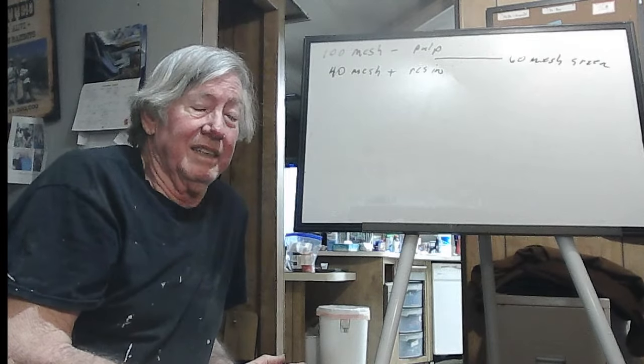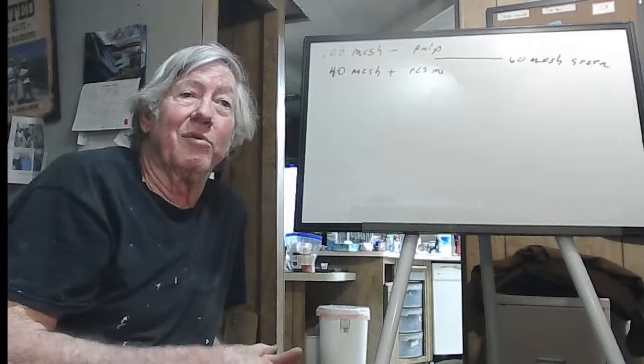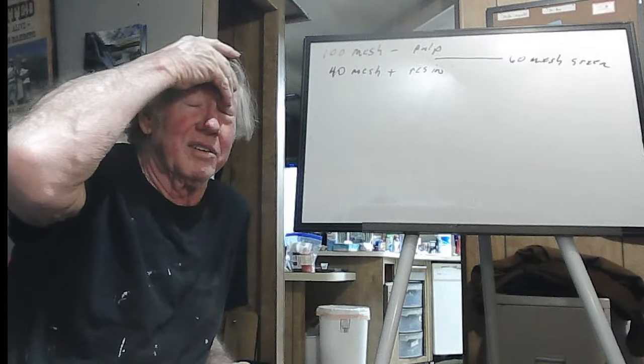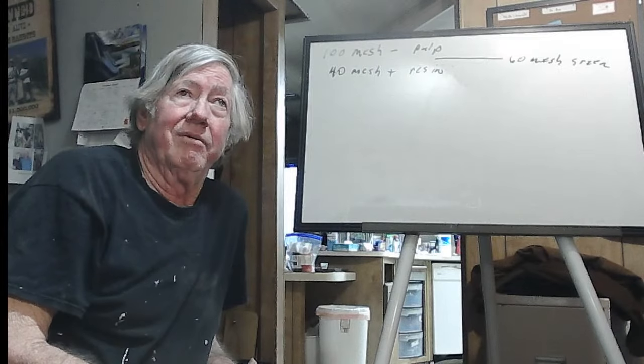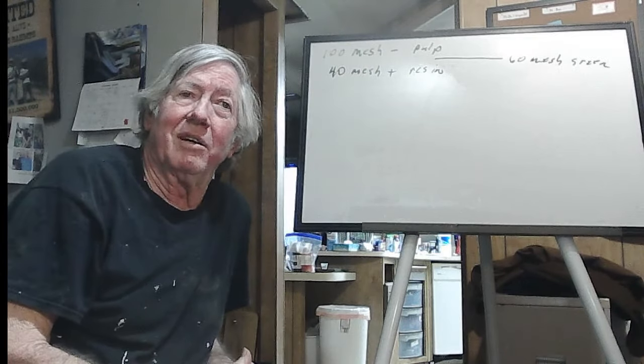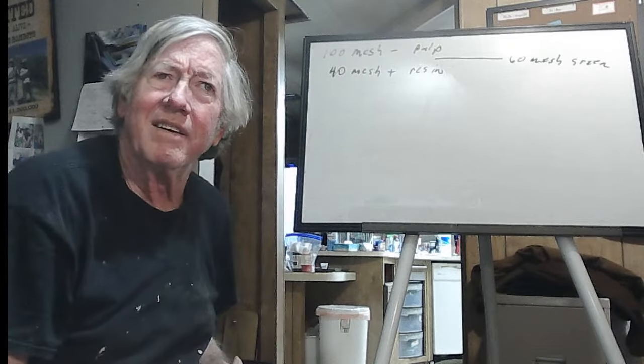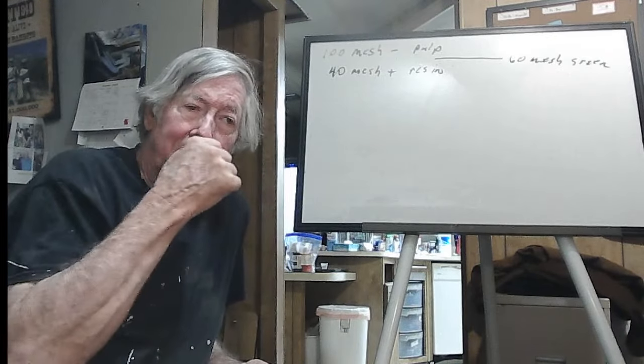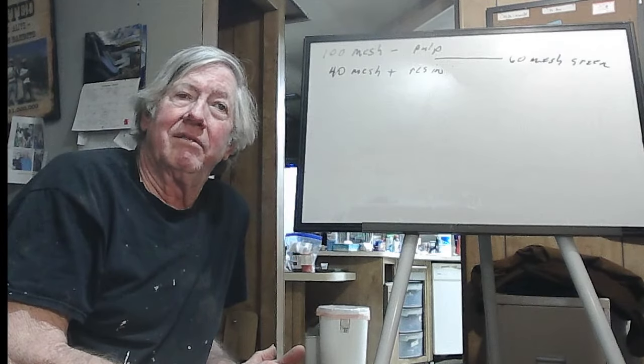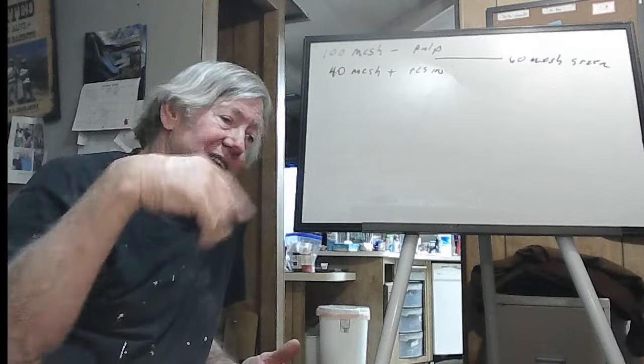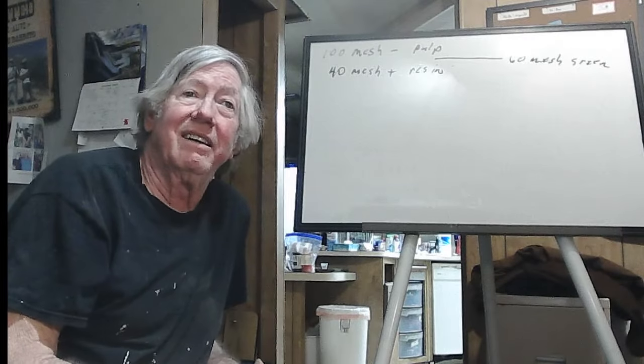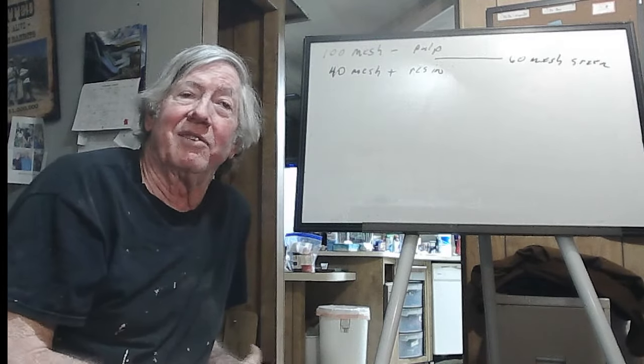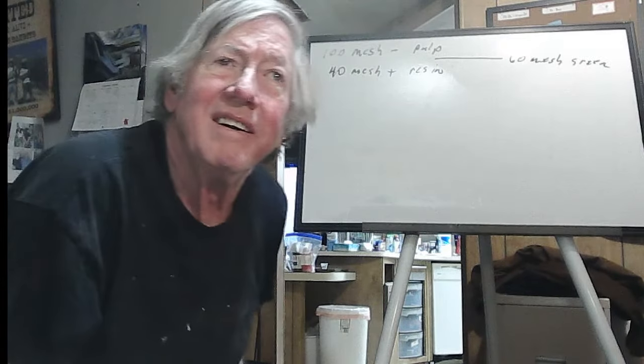Okay? Then you go ahead and just, if you need to regrind it smaller in order to get better recovery, which was the recommendation from the manufacturer, from Eco Goldex, and it makes perfect sense. You could take your sulfide cons, put them in the little mini ball mill, which can easily handle 100 pounds a day. Grind it for a certain period of time. Have to determine what that is. I'm guessing, since it's a batch process, throw it in there, run it for a couple hours. You're probably well under 200 mesh. Okay.